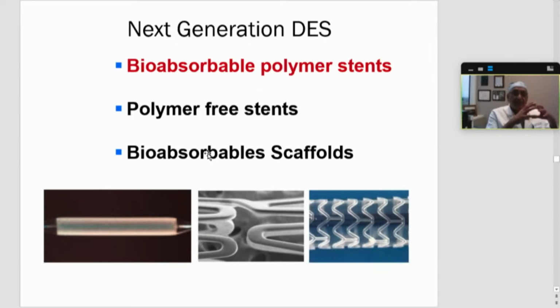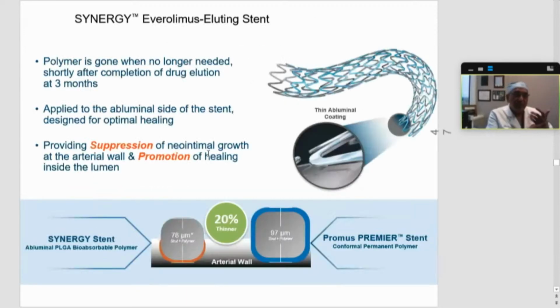And this kind of divides into three categories: the bioabsorbable polymer stents, polymer-free stents, and then bioabsorbable scaffolds. So Synergy is the one which has been in the U.S. market for several years, and it has a bioabsorbable polymer. The polymer is gone after the drug is eluted, which is basically after 3 months. It is only applied to the abluminal side, so it is not where the blood is flowing, but more towards the vessel wall, which I think is a smart design. And that leads to suppression of neointimal growth at the arterial wall and promotion of healing inside the lumen.